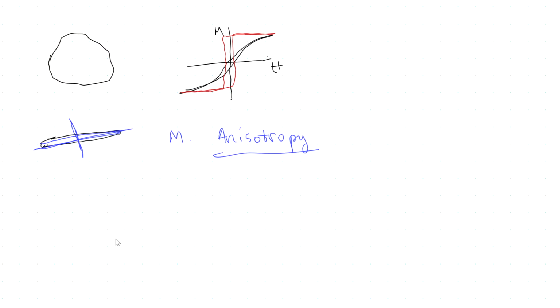Well, if you remember, we discussed vibrating sample magnetometry. As part of the magnetometer you have a magnet. I schematically designate north and south poles, but these are electromagnets, so they can be switched. In this case, the magnetic field is in this direction. If you place the sample in this direction or in that direction, our field would be aligned with different axes of the material, and we would be able to measure magnetic properties along the material or perpendicular to the axis of the material.